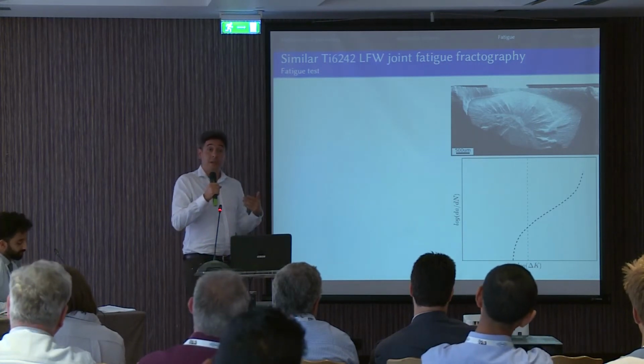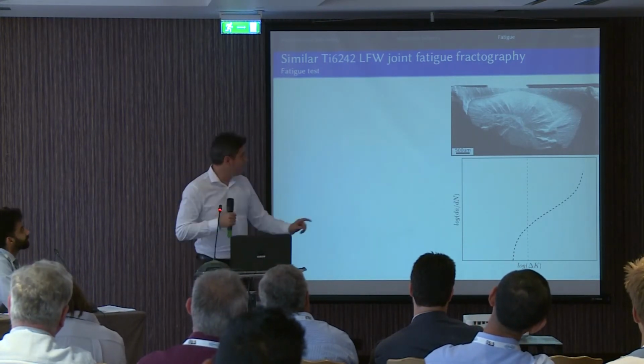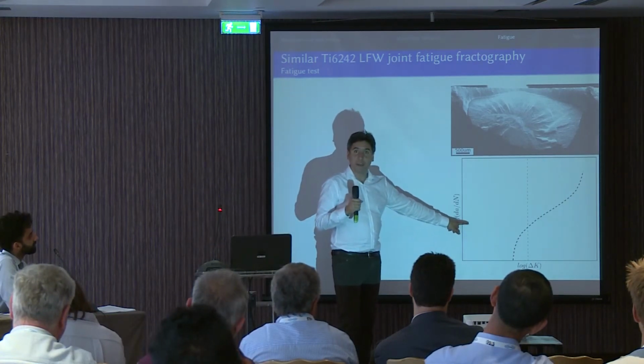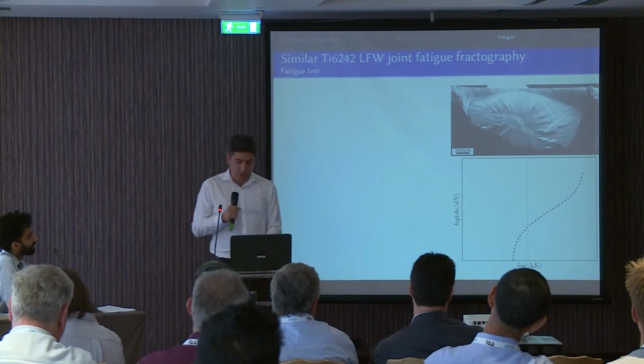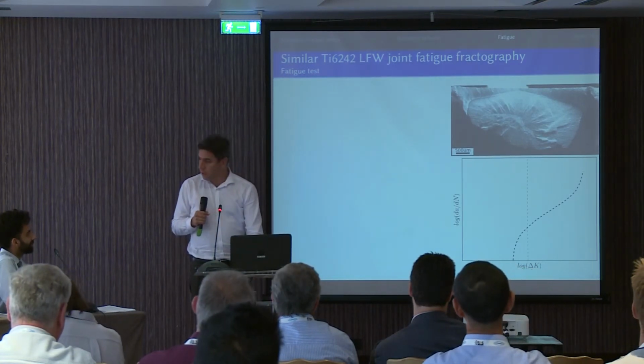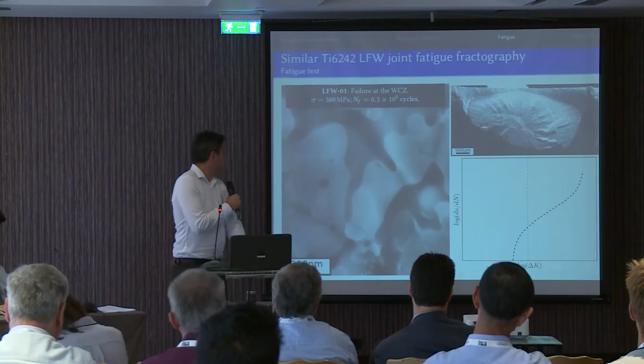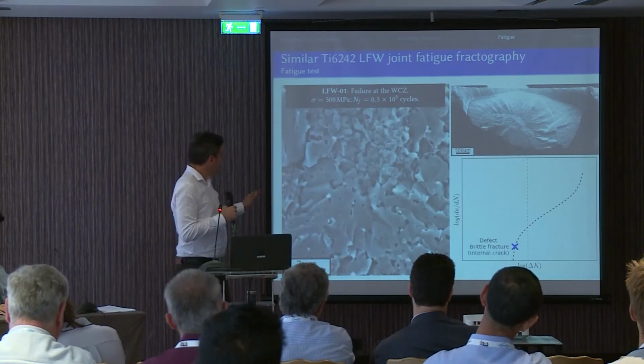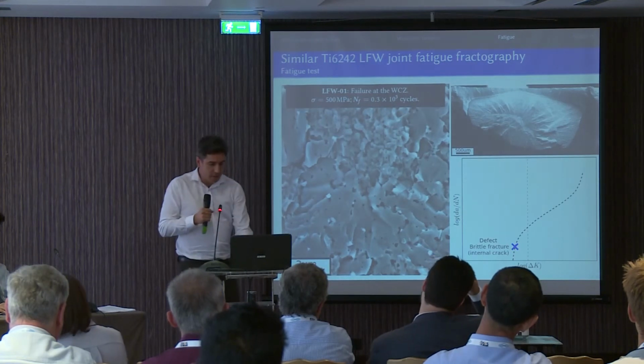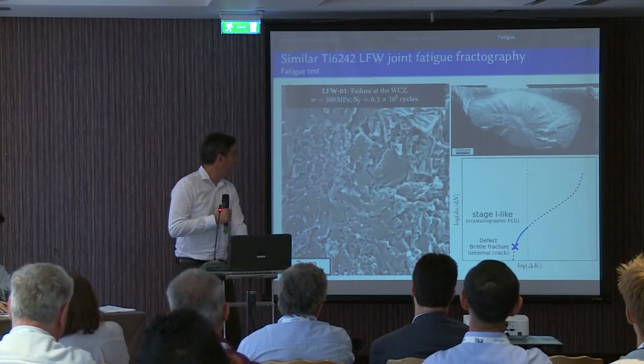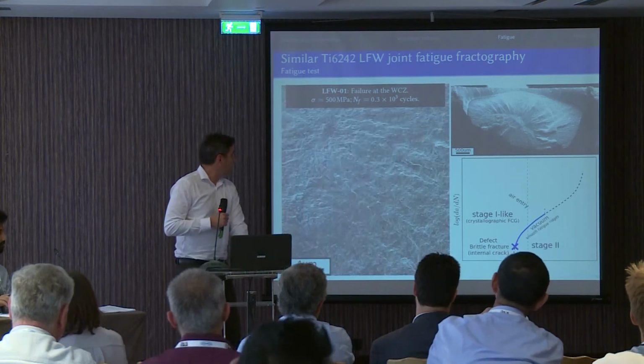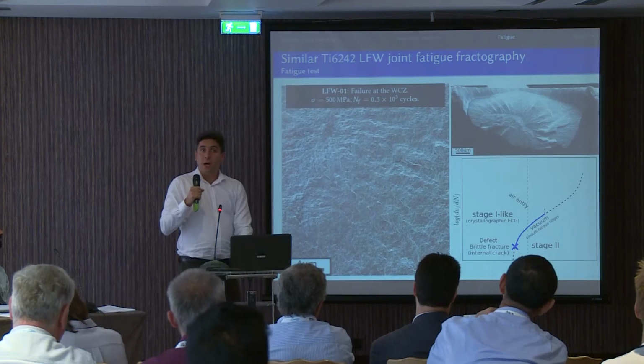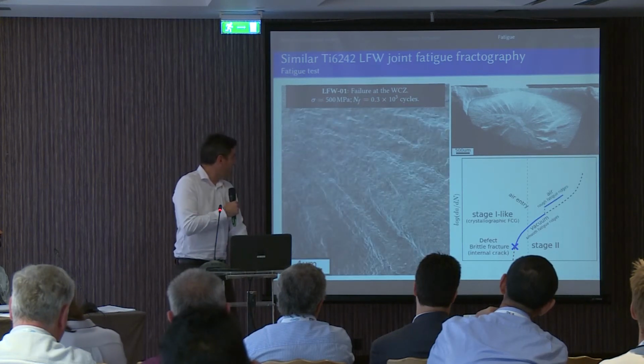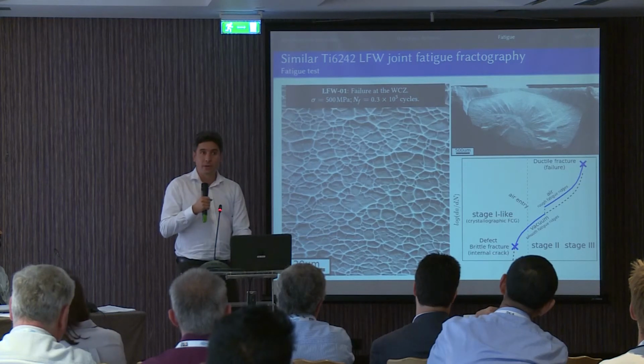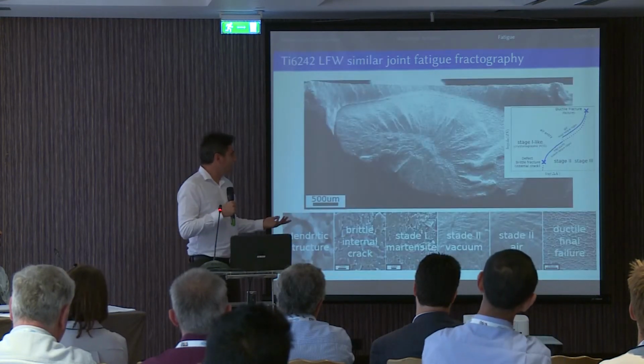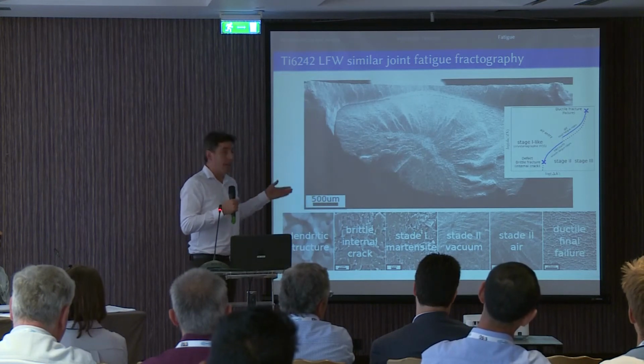So now we can imagine the fatigue crack propagation scenario. This is going to be a schematic image. I have not measured the crack propagation rate. So we have the brittle defect. We have a brittle fracture in its surroundings. We have the fatigue crack propagation over the mountain side. We have stage 2 fatigue propagation in vacuum until the air comes in, and finally we have a ductile final rupture. This is very interesting because we have several mechanisms in the same specimen.